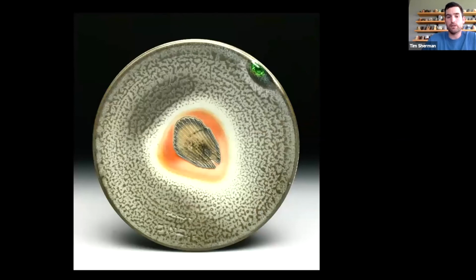Probably the second most, and I'm sure it's not because of me, it's just a natural thing that would happen with big kilns, is that I put soda, in our case baking soda, in the back third of the big kiln. And the reason for that is I was just used to seeing people unloading the back of their anagamas and having dry brown pots or concrete looking surfaces, and I just was not interested in that. So my solution was to throw baking soda in the back of the kiln, and that has become, for most people, myself included, one of the best spots in the kiln, that back third.